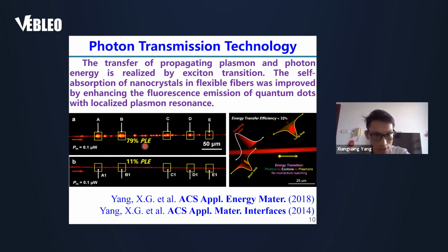In figure A, the A, B, C, D, and E positions are with gold nanorods, and A1, B1, C1, D1, and E1 are without gold nanorods. The PL efficiency was improved from 11 percent to 79 percent. Also, we published the results in these journals. If you have interest, you can download them.